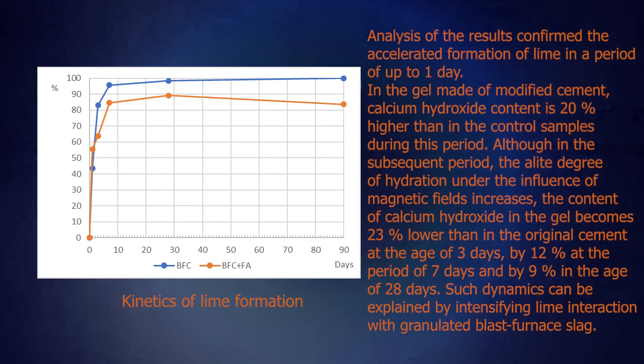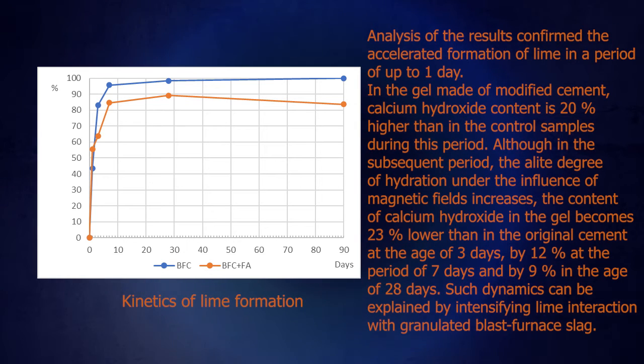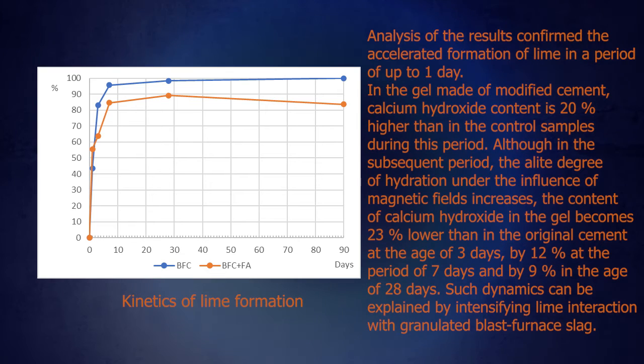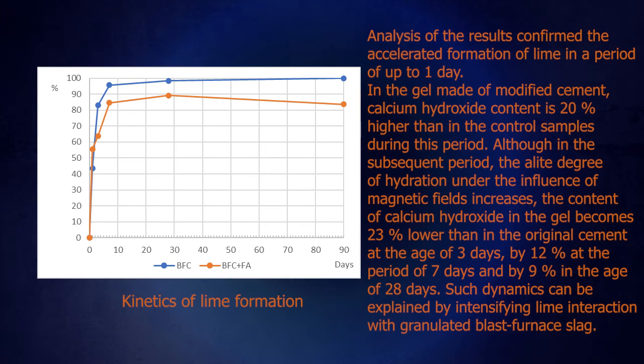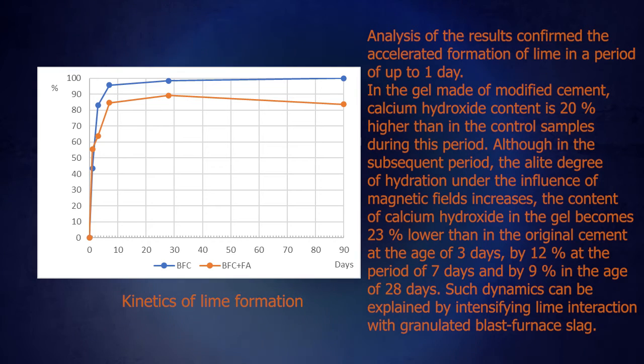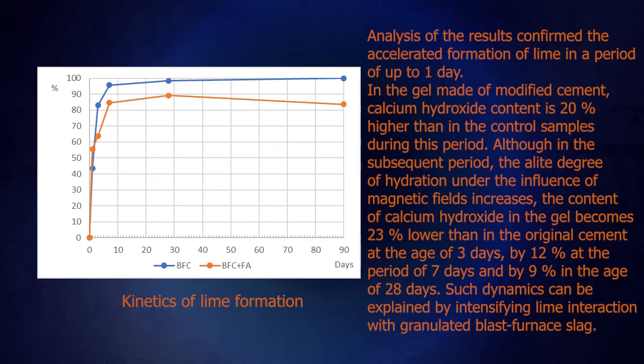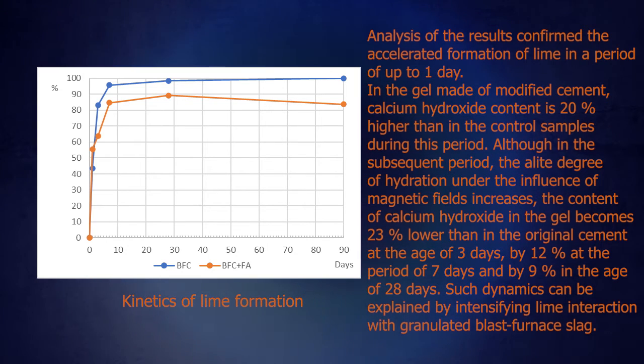Also, in the subsequent period, the alite degree of hydration under the influence of magnetic fields increases. The content of calcium hydroxide in the gel becomes 23% lower than in the original cement at the age of 3 days, by 12% in the period of 7 days and by 9% at the age of 28 days. Such dynamics can be explained by intensifying lime interaction with granulated blast furnace slag.